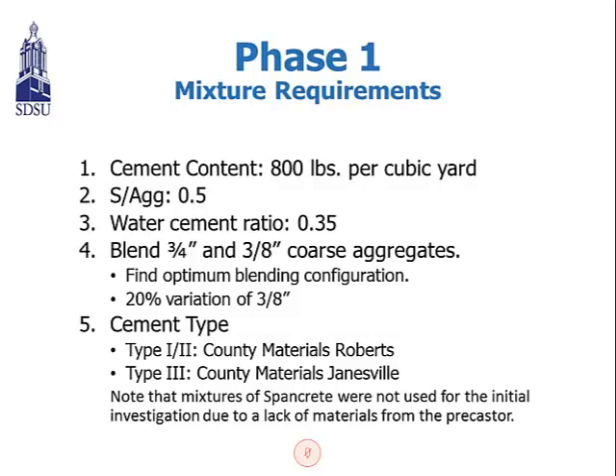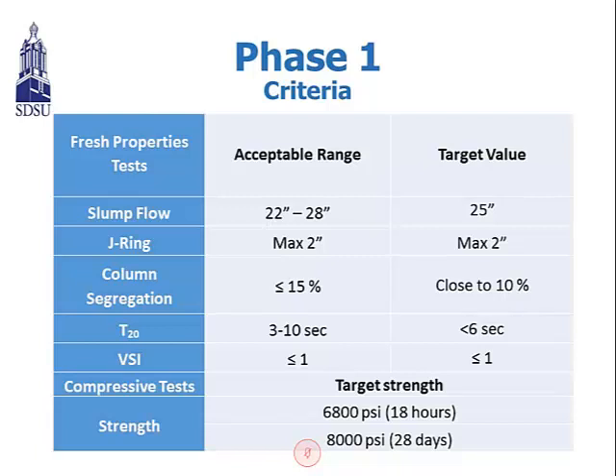So first, we prefer to use 800 pounds per cubic yard, a sand aggregate ratio of 0.5, and a water cement ratio of 0.35. And we use a blend of 3/4 inch and 3/8 inch coarse aggregate using material from County Materials. And we use two types of cement, type 1 and 2, and type 3. And this is the criteria that was used to identify the most satisfactory mixtures.